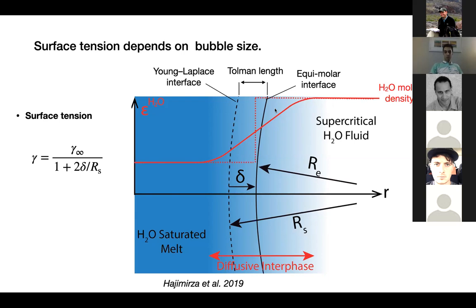Tolman, in his seminal 1949 paper, started with this theory of surface tension by Gibbs and developed a formulation for surface tension of nanoscale bubbles. This is basically a correction of surface tension based on macroscopic measurements, which says surface tension of nanoscale bubbles depends on their size and a parameter called Tolman length, and depends on the properties of this interface.